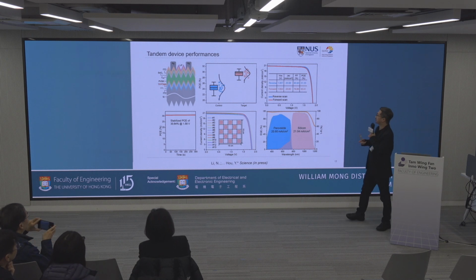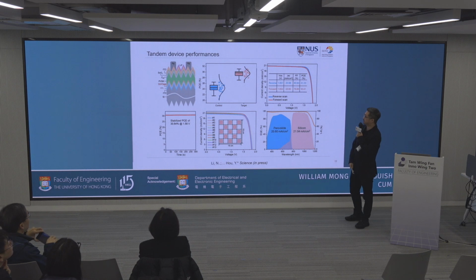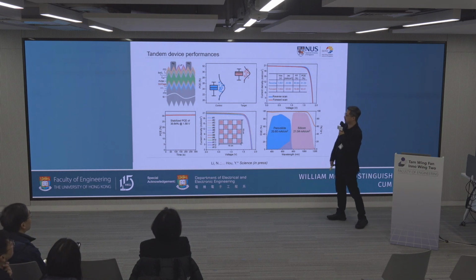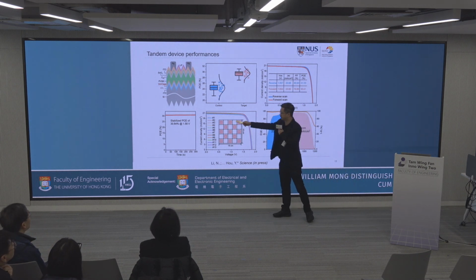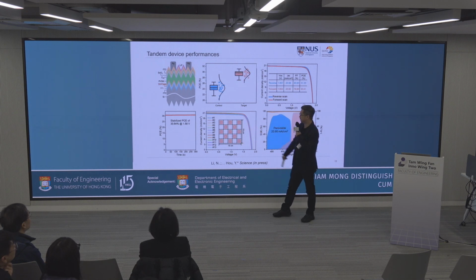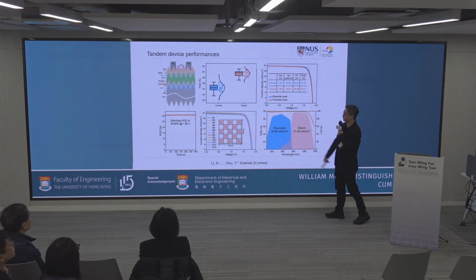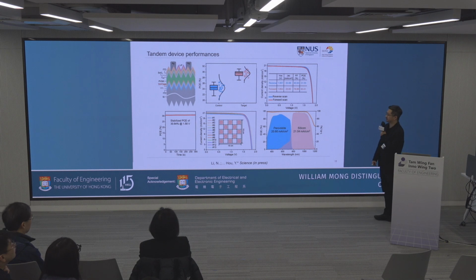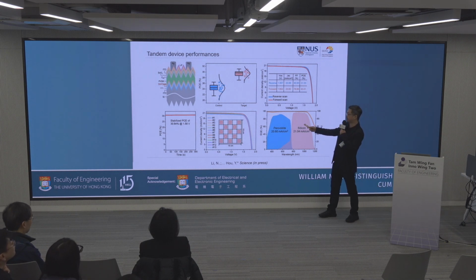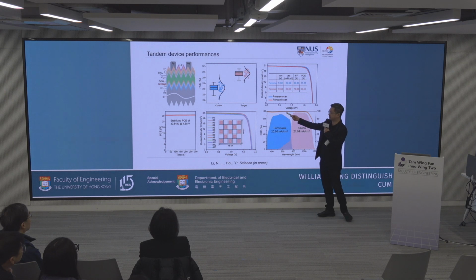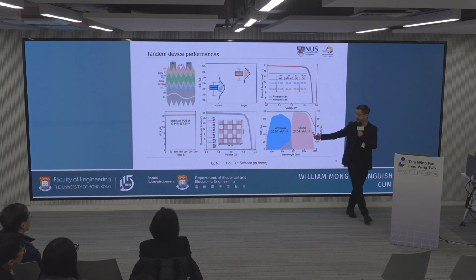And the performance is around 30-31%. And it was very homogeneous. We put it at a different spot at this 18 by 18 cm area, and you can see very close performance. And because it's a conformal growth of perovskite on the pyramids, you can see the reflection is very small, and the EQE response actually is very good.